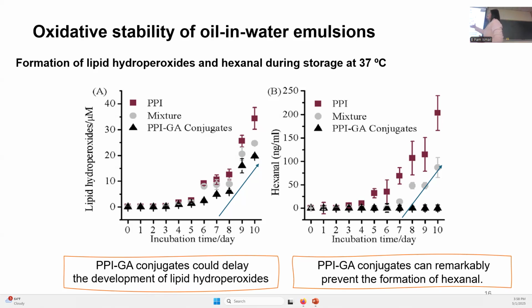So the author concludes that the conjugates could delay the development of lipid hydroperoxides compared to pea protein alone and the mixture. And then in the second one, we can also see that the hexanal started to appear after these 7 days of storage, but the conjugates remained below the LOD, the limit of detection. So they concluded that the conjugates, PPI with gum arabic conjugates, can remarkably prevent the formation of hexanal in these emulsions.